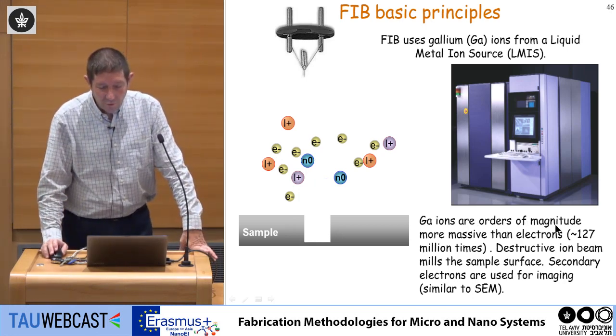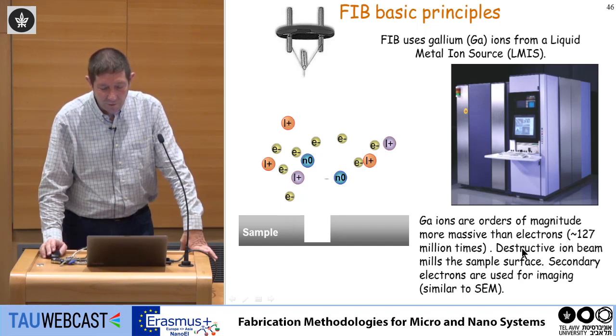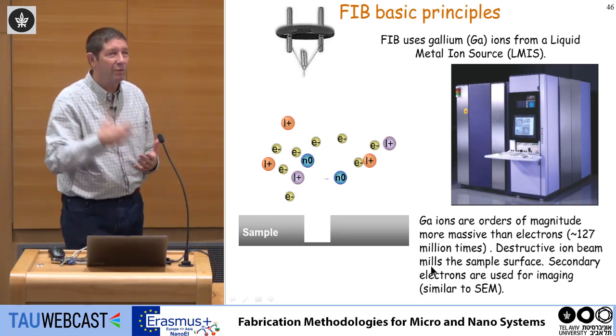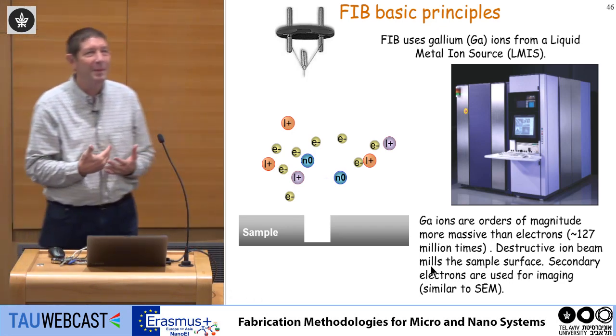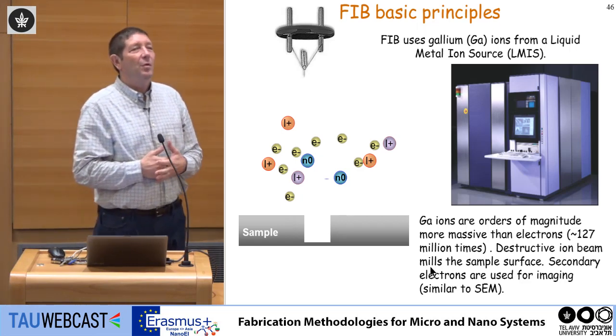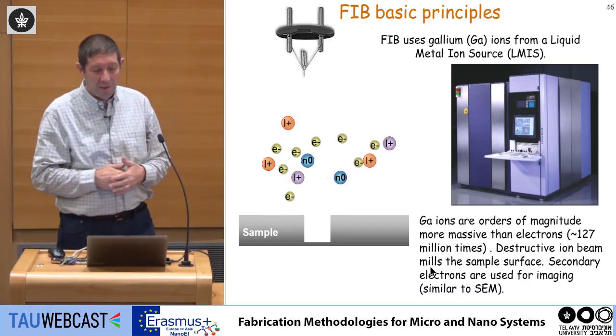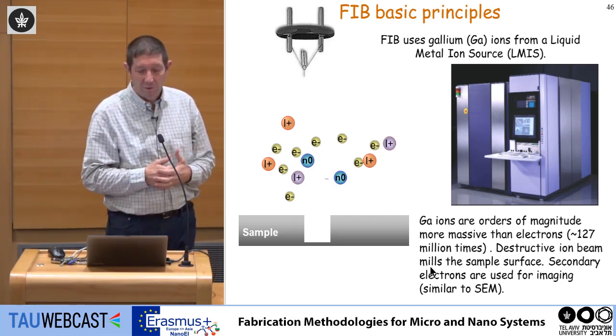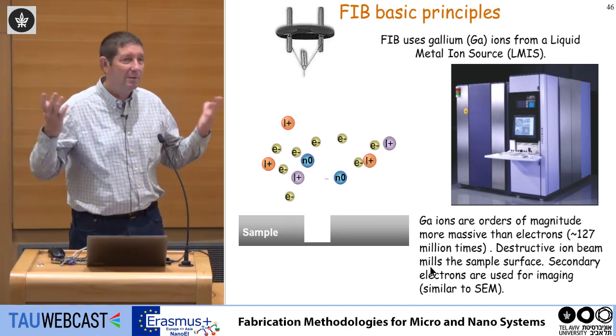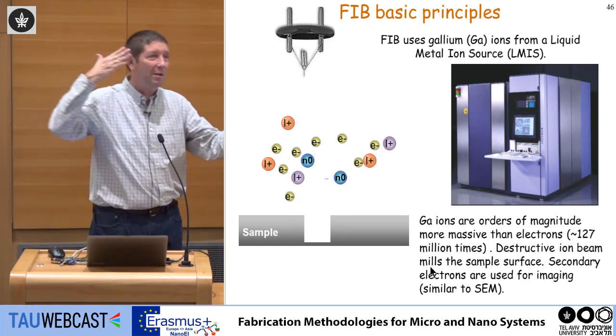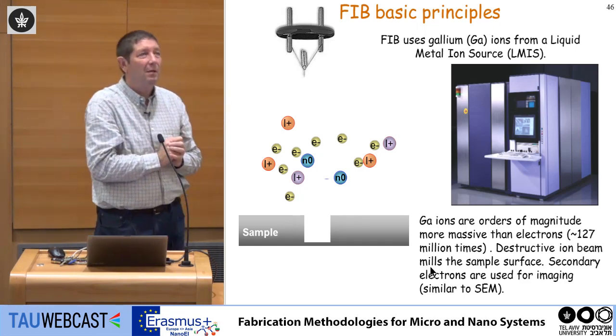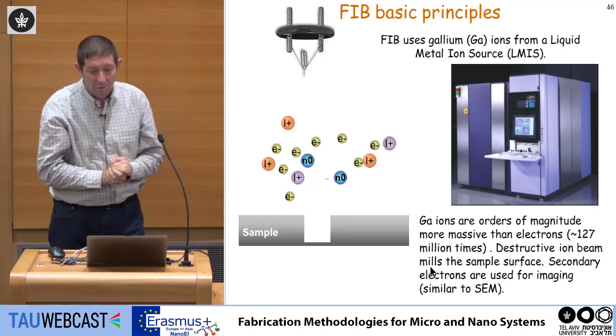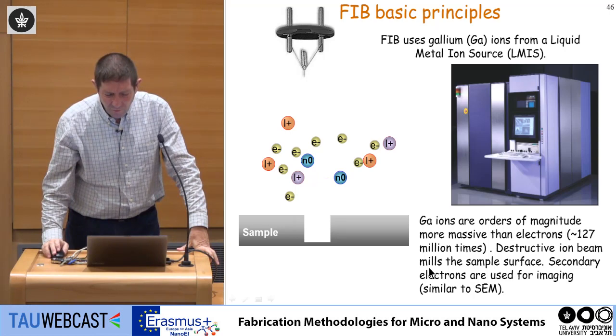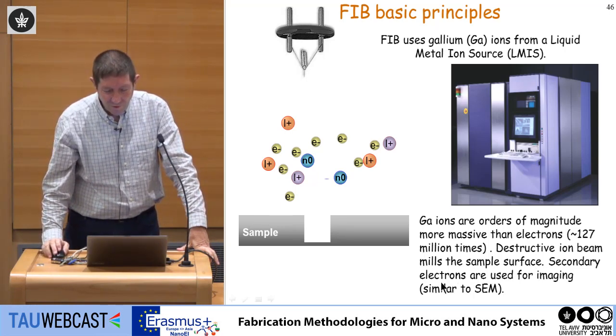And the gallium ions are orders of magnitude more massive than electrons, and the destructive ion beam mills. This kind of sputtering, removing material, we also call milling. Sometimes people call it ion beam milling, or ion beam sputtering, and sometimes ion beam etching. But the fact is that the ions hit the surface and break the structure, and molecules are being emitted. All these are synonyms. So the destructive ion beam mills the sample surface, and secondary electrons are used for imaging.